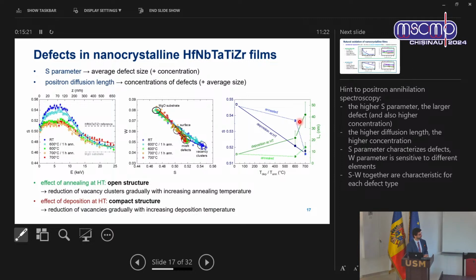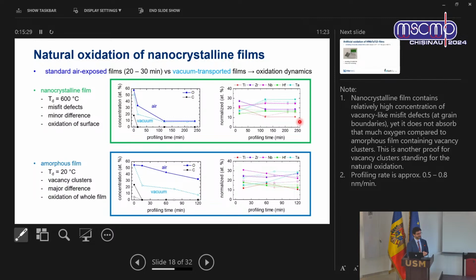And the impact of these different defect structures on the oxidation properties is demonstrated by this experiment. We needed to characterize the dynamics of this natural oxidation. So we compared XPS results of two types of samples. First one was normally exposed to the air, transported to the XPS apparatus within the time scale of 20-30 minutes. And the second type of samples were transported using the vacuum suitcase, so without exposure to ambient air. And here we compare the film which is amorphous, the one which should extensively oxidize, and the film which is nanocrystalline. And I have to say, nanocrystalline, but with still relatively large concentration of vacancies, but without vacancy clusters.